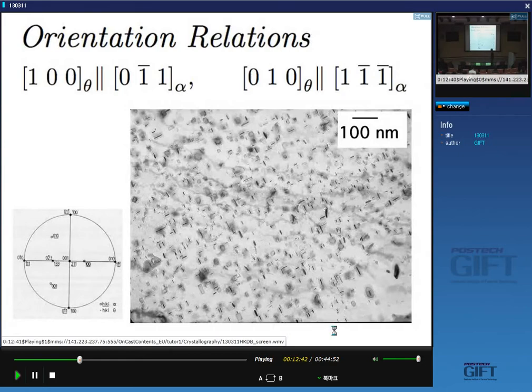So we routinely talk about orientation relationships between precipitates and the matrix, whether it's cementite and ferrite, or austenite and ferrite, or molybdenum carbide and vanadium carbide, sulfide, and so on. They are important in determining the properties of the material, and that's why we bother to measure them and to study them and to calculate crystallographic textures and so forth. So these can be represented on a stereographic projection, and I'll show you how to do that.